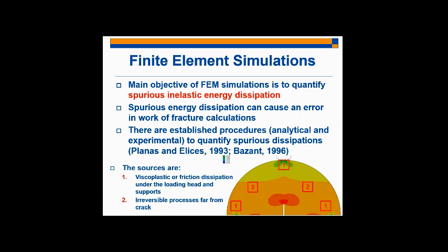So one of the issues that we potentially could face when testing at intermediate temperature, at 25 degrees Celsius, is complications with the fracture energy values that we are extracting. So there are two primary areas of concern when testing at 25 degrees Celsius. The first area of concern is complications at the loading head, which is signified by the 1 here, and also the roller supports. So you want to make sure that there isn't any significant deformation at any of these points. Otherwise, the displacement results you're getting are kind of tainted.